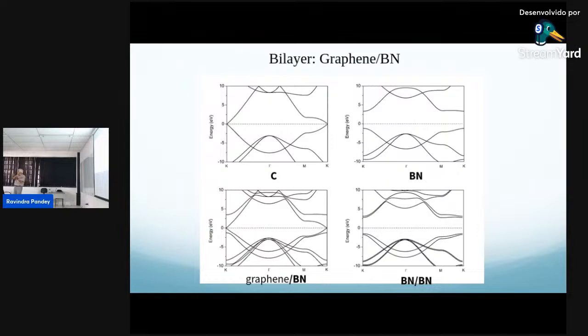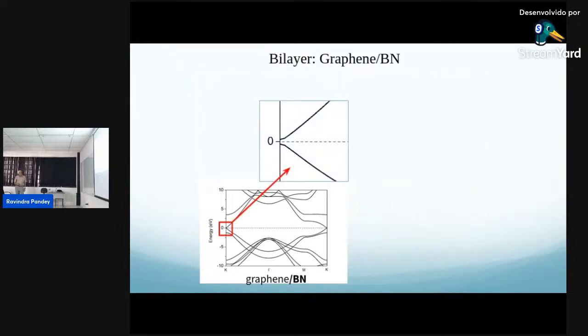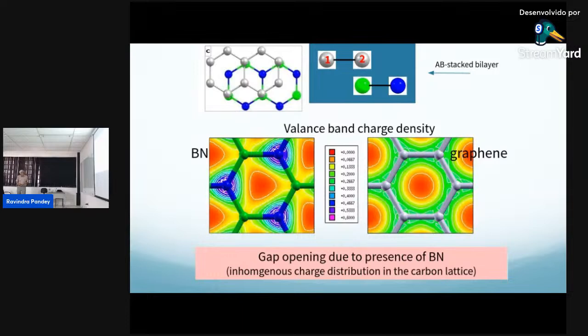So when the student showed me this the first time, I said something is wrong. He said, let's zoom in, because the interaction is going to have very, very small gaps. So he zoomed in, and you can see it's about a milli electron volt opening of the gap. Now we had to do some experimentation to see if it's correct or not. So our hypothesis is, if gap opening is due to this inhomogeneous charge distribution in the carbon lattice, because of the interaction, what happens if I reduce the interlayer distance? It's going to have large overlap of these electrons. It's going to have a large opening of the band.